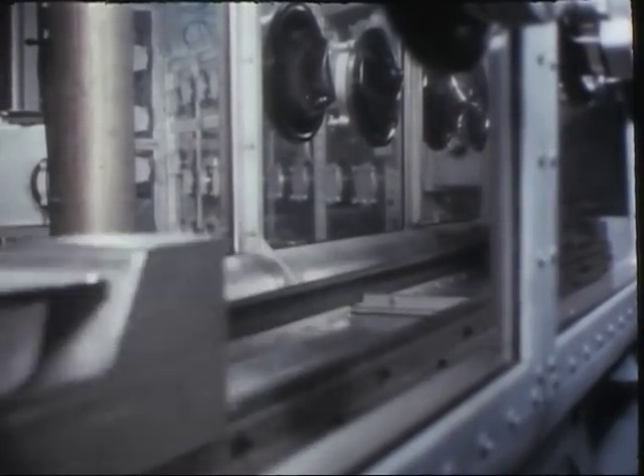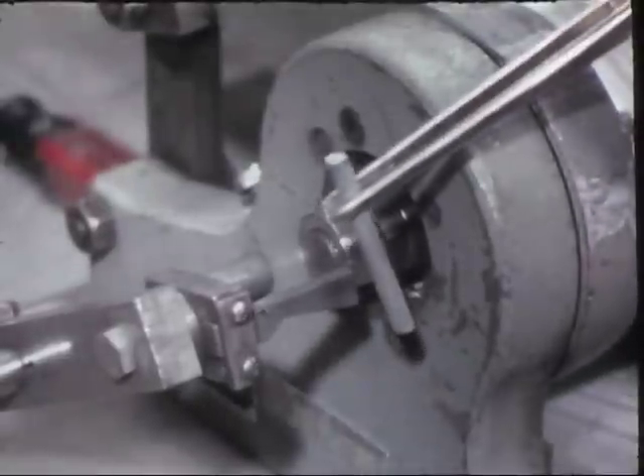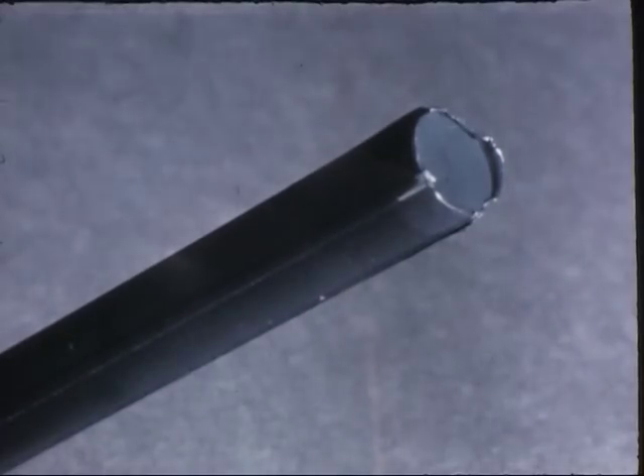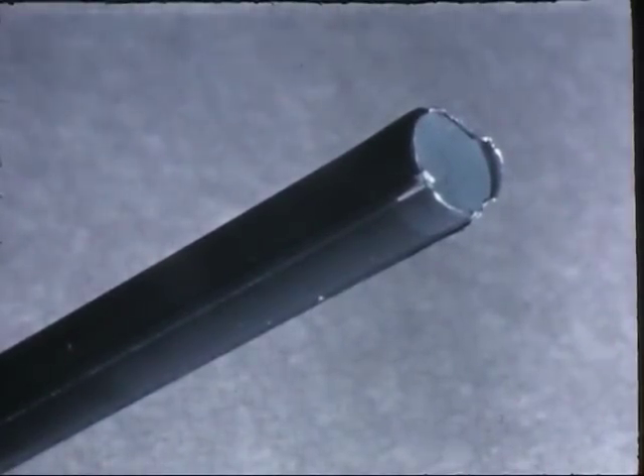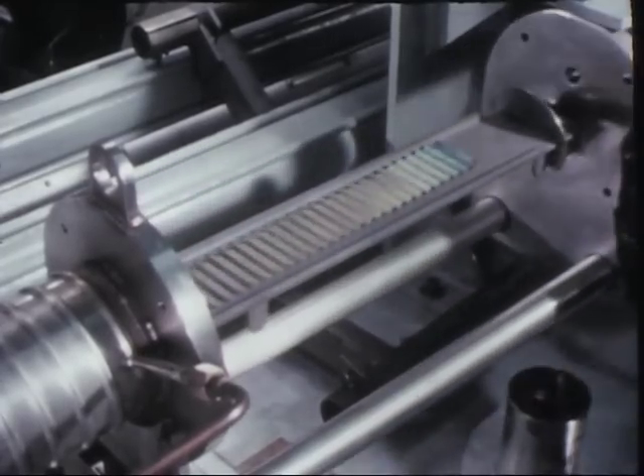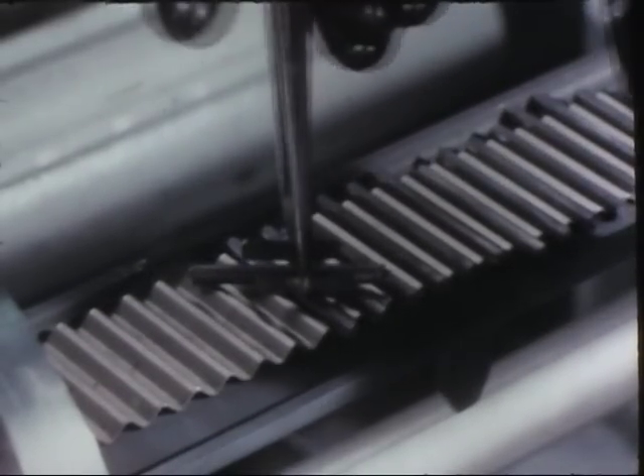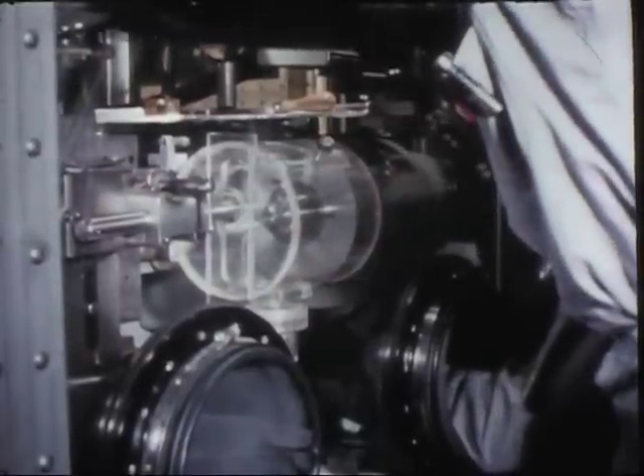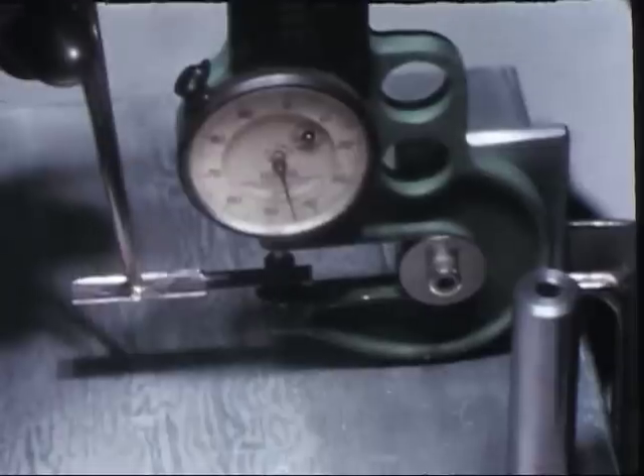After breaking the glass molds away, the castings are rough cut to produce slugs two and one-eighth inches long and the scrap rod returned for remelt. The slugs are coined and densified in a double-plunger die at 180,000 pounds per square inch to produce the final diameter and longitudinal ribs. The fuel slugs are annealed at 400 degrees centigrade in a vacuum tube furnace before machining to final length. The lathe is mounted on its side for convenient access to the controls and a plastic hood collects turnings. Finished fuel is inspected for surface imperfections, diameter between and across the ribs, weight, and straightness.